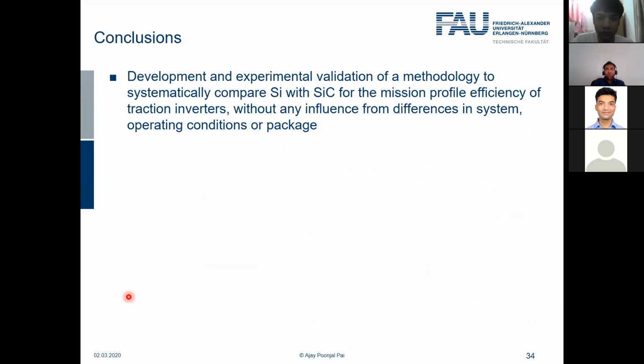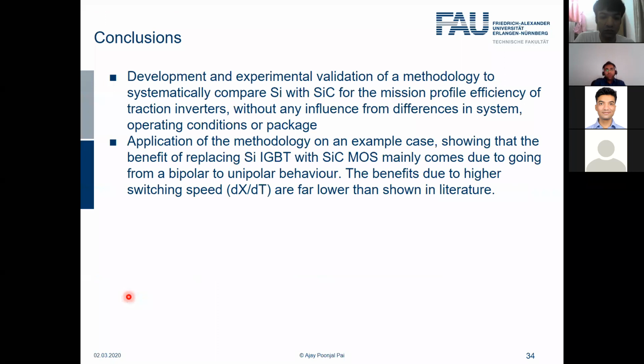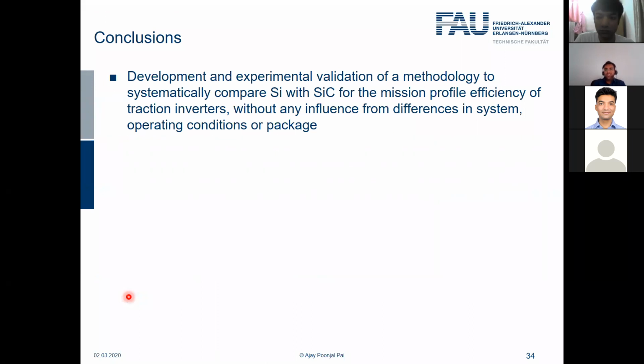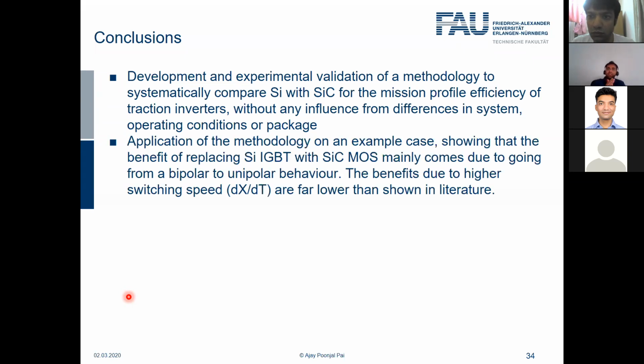Okay, so with this, I go to the conclusions. The goal of this thesis, like I said, was to compare silicon and silicon carbide one-to-one for the traction inverter application from the point of view of mission profile efficiency. And this we did. For this, it was necessary to come up with a power loss model which is accurate enough to see the difference in the technologies, and which is also capable of splitting the power losses into different components. And we saw that most of the benefits of silicon carbide come because we are going from a bipolar to a unipolar behavior.